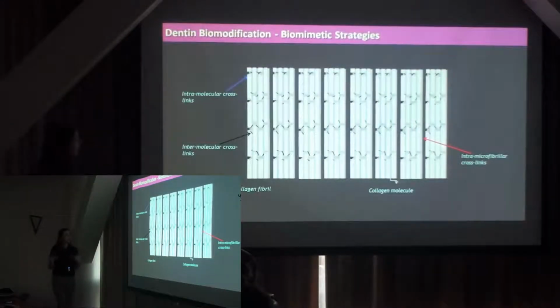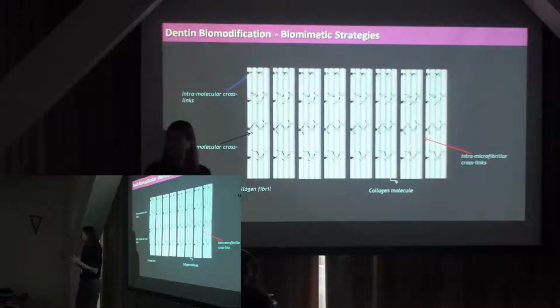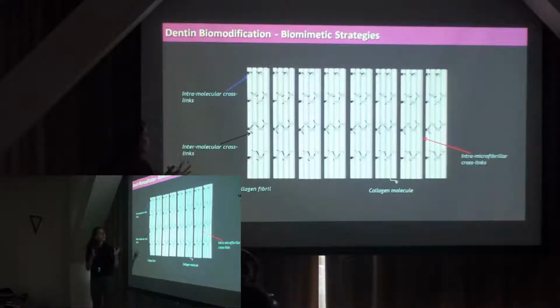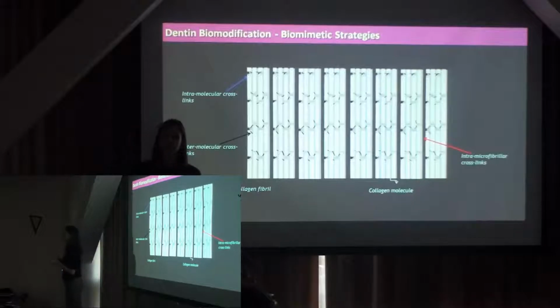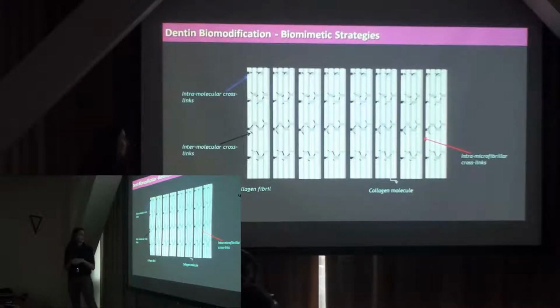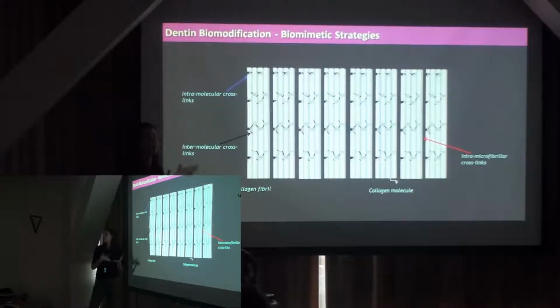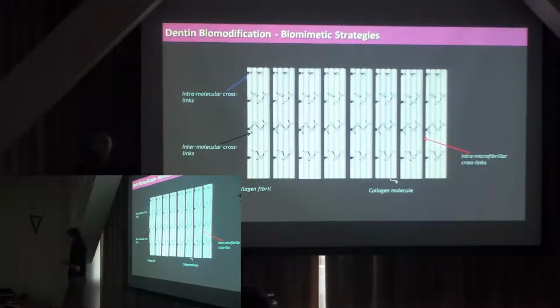So basically we got our inspiration from nature. We realized, okay, in the tooth we have all these collagen cross-links that stiffen the collagen and reduce the degradation rate. What if we start introducing additional cross-links at that interface, and let's see what happens.